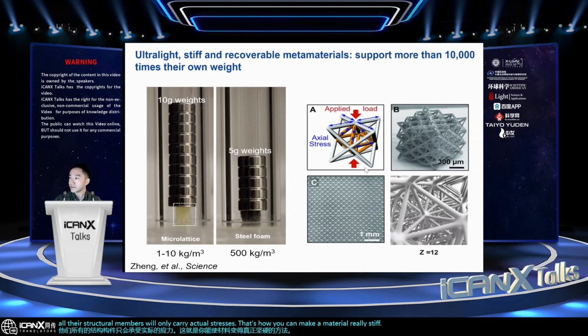And if you tessellate these micro unit cells, repeat them over three dimensions, and replicate these units over hundreds to millions of unit cells together, that really gives you a metamaterial. And if you can shrink the size of this ligament, especially the wall thickness, to a few microns to tens of nanometers, you can make them really lightweight so that their volume fraction, the fraction of solids within the cubic volume, can reach less than 1%. So 99% is air, and only 1% is the solid material that carries the weight.